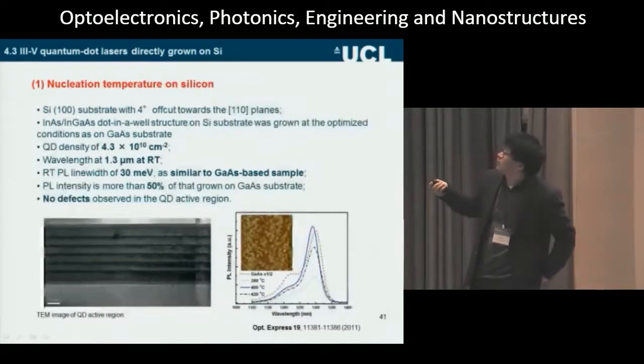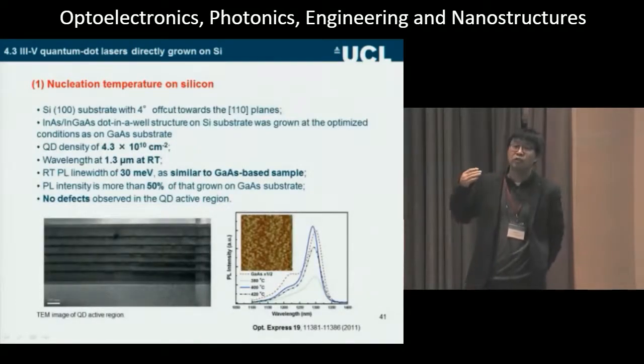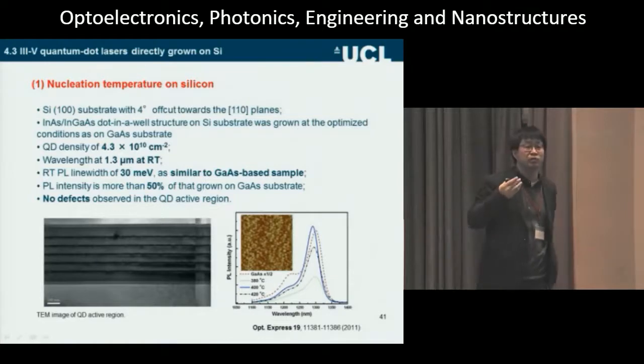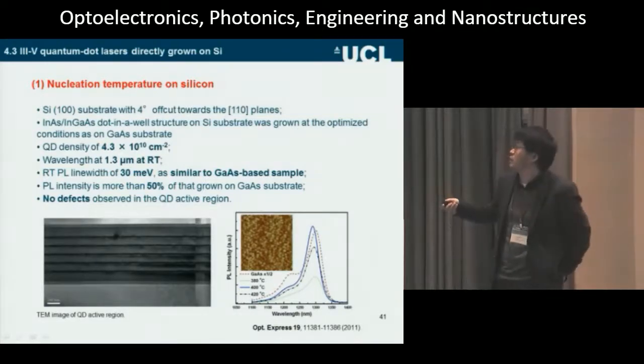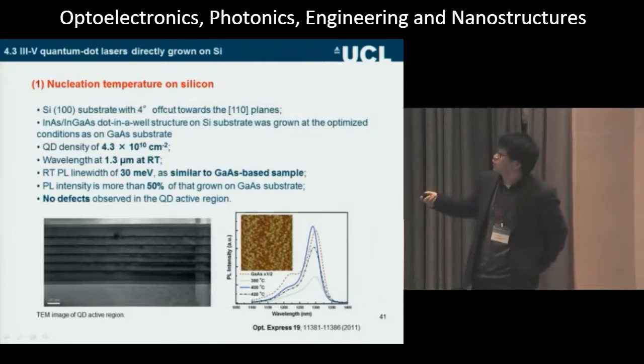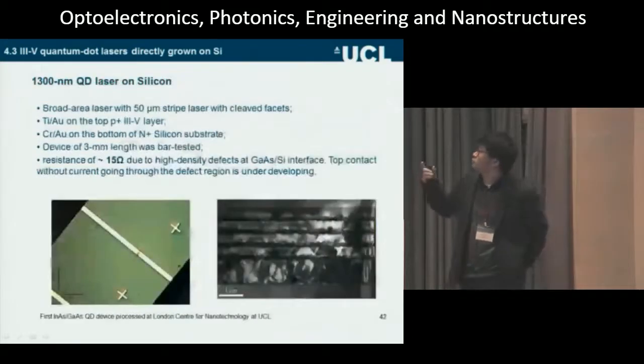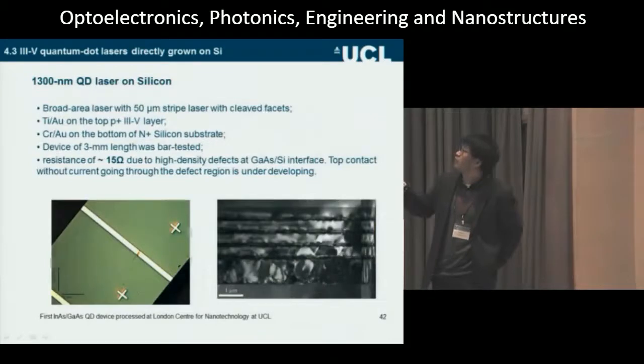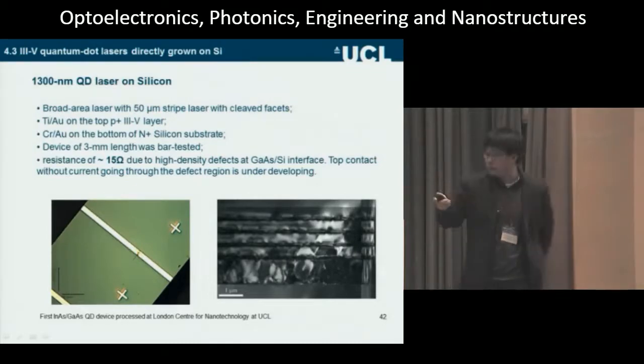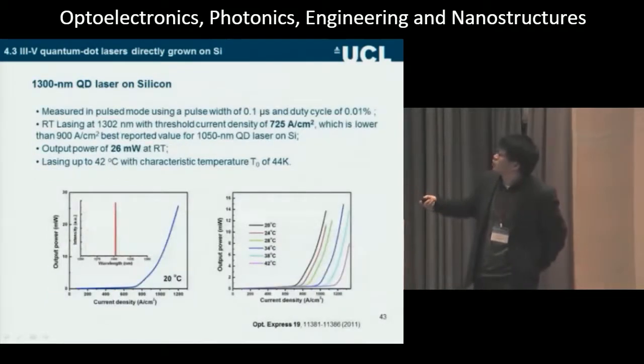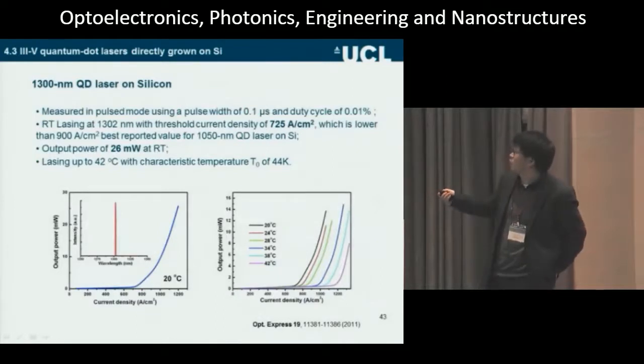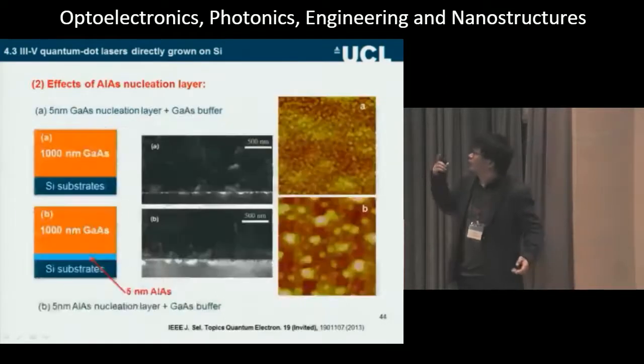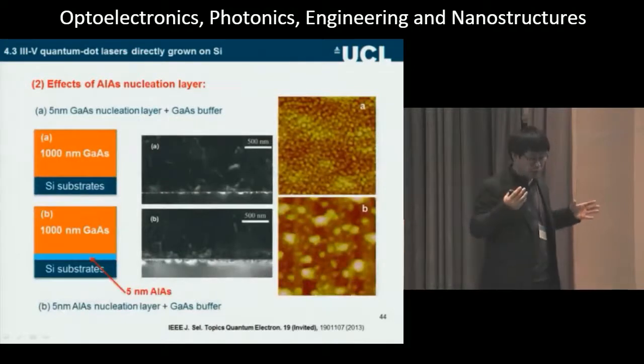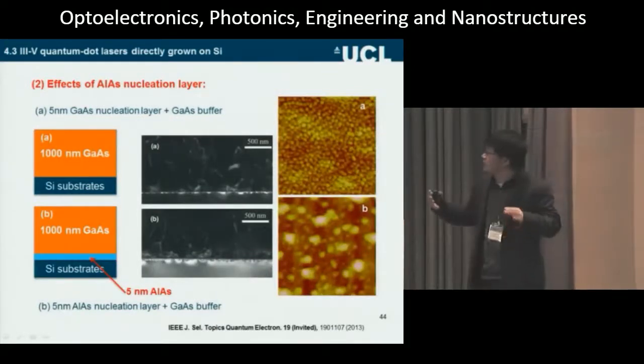So first thing is nucleation temperature. You need to grow gallium arsenide at a very low temperature so you don't form a lot of defects, and you also get flat growth. We use this method, and we get very good quantum dots and very good emission. After that, we made the first laser. We make the contact from bottom to top. The resistance is 15 ohms, so it is hardly a diode. Even like that, we still got a laser at room temperature at 1.3 micron for the first time, and the laser worked up to 42 degrees.